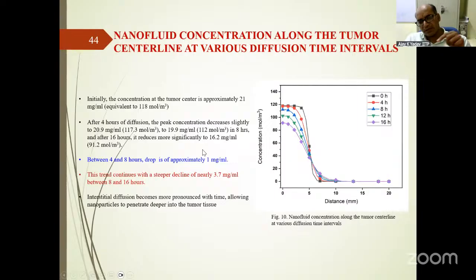This part is when we are injecting nanofluid, how much time that nanofluid, the nanoparticles, will be there in the tumor. So you can see here, initially at 0 hours, and distance is also mentioned here. You can see up to 4 hours, this is the 4 hours. Then this is around 8 hours. But up to this 5 mm distance, 5 mm is your tumor part. After this 5 mm distance, we are able to maintain around.